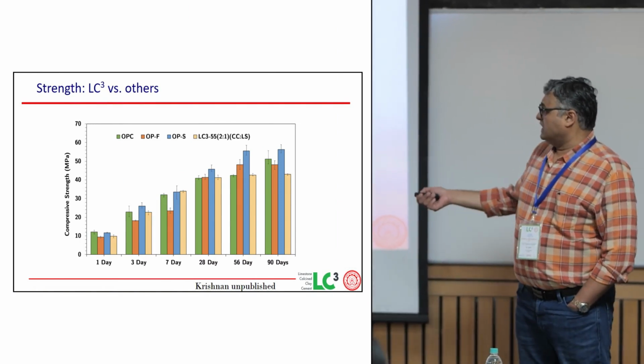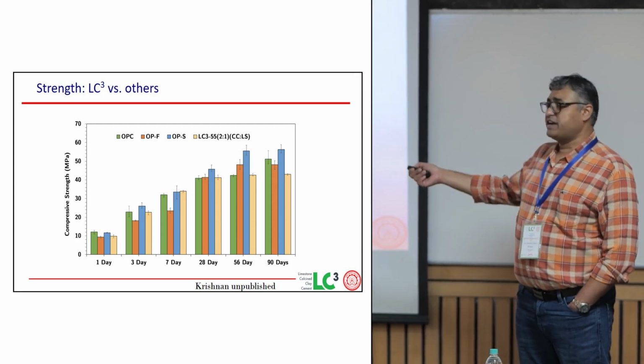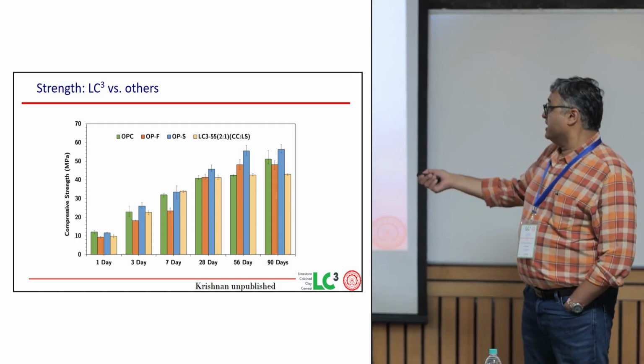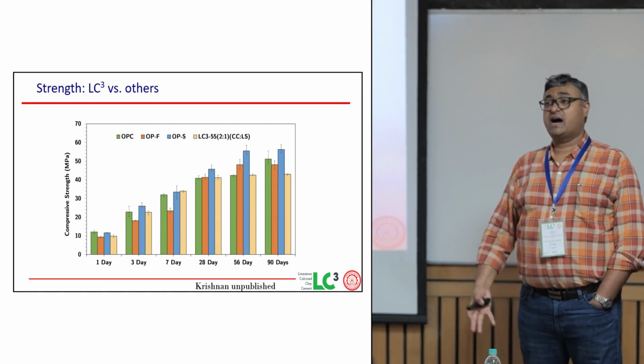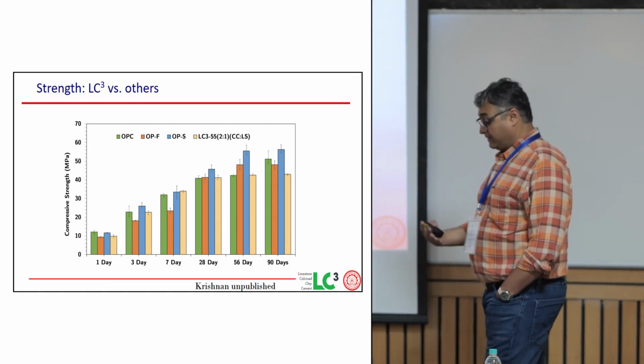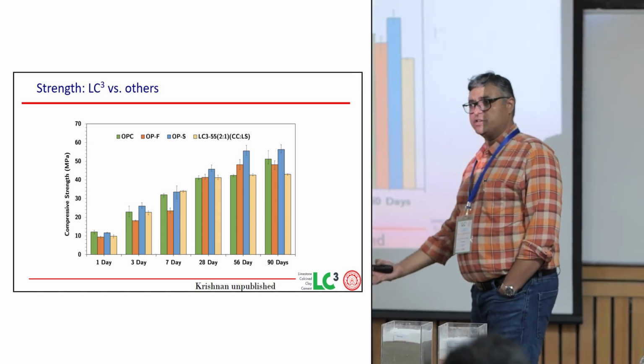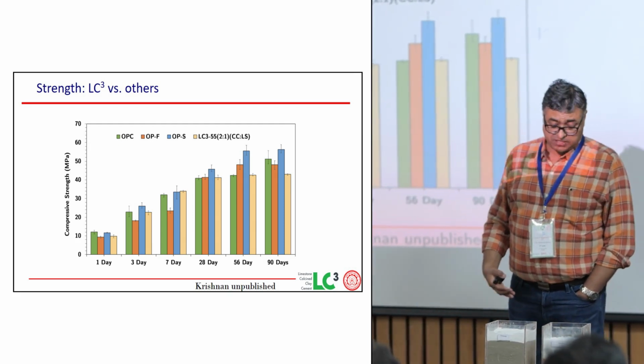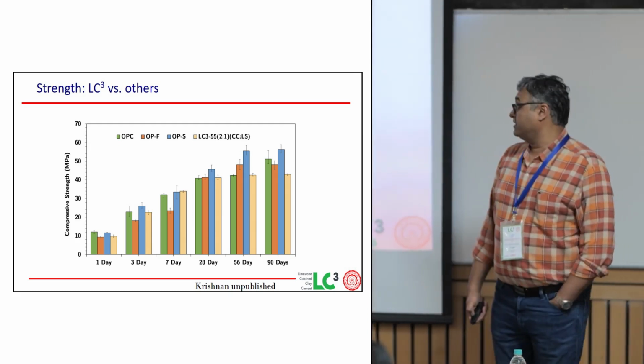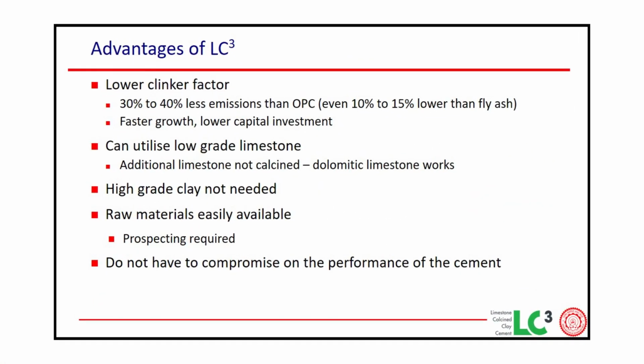Even though the early stage may be a little bit different, we found that at 28 days you were getting the same strength. At 7 days we were able to get sometimes higher strengths than OPC, and that was very encouraging for us. These are very old results. We wanted to understand why this is happening, and then we wanted to understand what about the other properties of the cement and the concrete. Those are the things that you're going to hear about in this workshop.